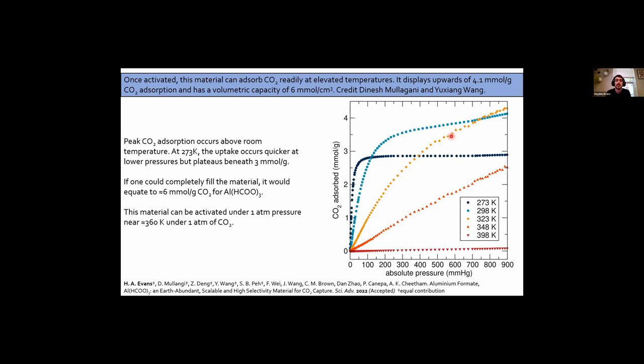So we looked at how CO2 goes into this material. And you can see that it sucks up CO2 and it does it at high temperatures and it does it really, really well. You can see that this peak absorption at this high absolute pressure from this CO2 adsorption isotherm is at about 323 Kelvin, so that's 50 degrees Celsius. We're aiming at temperatures where we're coming off of an exhaust stream, and that's where we think we're going to see the most use from this type of material. This is going to be a pretty good carbon capture material in and of itself because it works at high temperatures. It has all these other benefits that I can't really go into, but you will see this work come out in the next 2 weeks. And I'll tell you right now, it's been years that we've been working on this, so we're so excited to have it published finally, which is why we're talking about it now.